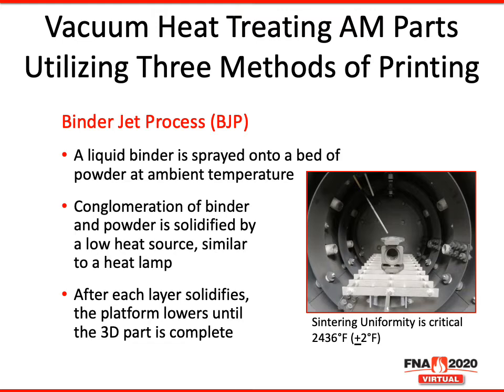You'll see the inside of a vacuum furnace with the type S thermocouple merely an inch or so from the part. The sintering temperature of this particular part is 2436 degrees Fahrenheit, plus or minus 2 degrees. So temperature measurement is very important. Temperature is just like when we do it in the MIM process. Dimension controls are tight. This particular part is an Inconel 625 piece that's being heat treated.